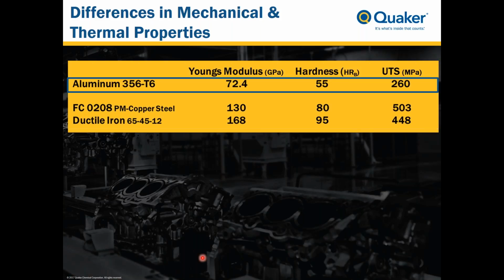Probably what's more important, though, is the elastic properties of the materials. And you can see the Young's modulus, often referred to as the elastic modulus, that gives a measure of how easy it is to elastically deform the materials under either a compressive or a tensile stress. And what you can see is that aluminum will start to deflect or elastically deform at a much lower pressure than will either of the two ferrous components. And this presents a situation that, again, under stress, whether it be a compressive or tensile stress during machining, the aluminum could start to deform at a much greater rate than the mating component, either the powdered metal or the ductile iron. So all three of these mechanical properties present some unique challenges because of the differences between the aluminum and the ferrous component.